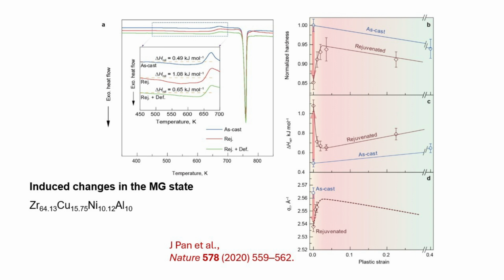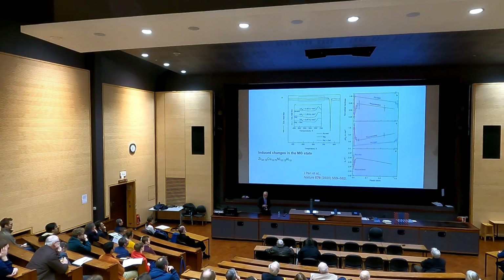When we deform that, it tries to revert to its original condition. So the hardness goes back up. That is our strain hardening. The energy comes down, and it becomes more dense. This is sort of neatly the opposite way around from G.I. Taylor. So G.I. Taylor's deformed specimens have higher defect density and higher energy. Our deformed specimens here, deformed after the pretreatment, are the other way around. They have lower energy and lower defect density, but they do harden.